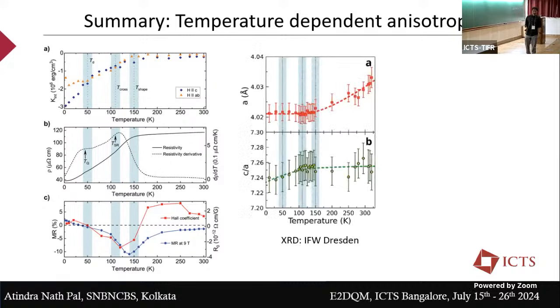Okay. So to understand a bit more, we did temperature dependent XRD measurement, to see whether there is any structural phase transition or not. This was also done in IFW Dresden, and they did a single crystal XRD measurement, and they observed as a function of temperature, it decreases, it behaves normally, it doesn't have a dramatic structural phase transition. So you can see the data, the C by A ratio is all within the error bar. So from this data you cannot conclude if there is a structural transition.